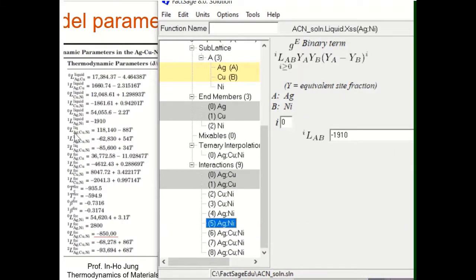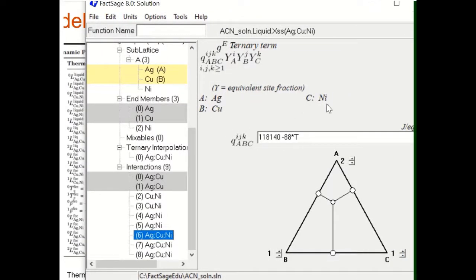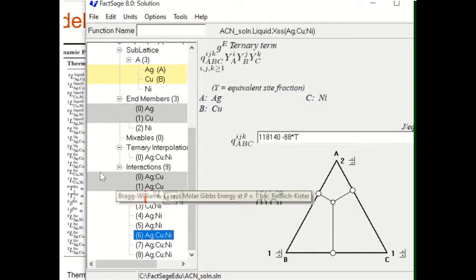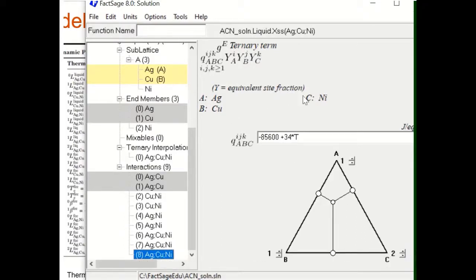Now for the ternary Ag-Cu-Ni system: the ternary excess term at power 1,1,1 by default. For the L0 ternary parameter, there is an additional power for the Ag side, so Ag to power 2, with Ni and Cu at power 1 and 1. For the L1 ternary parameter it's Cu to power 2, and for L2 the additional power of 1 goes to Ni. In this way I can add all the binary and ternary parameters one by one.